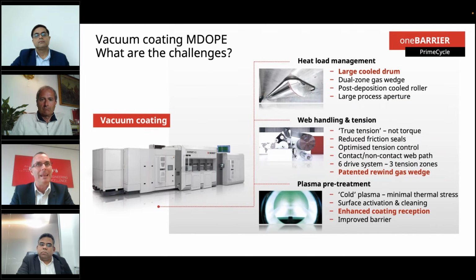We then move on to the metallization step of the structure. Typically, metallization on PE-based substrate is very challenging, as they're typically heat sensitive, extensible, and non-polar in nature. Now, MDO technology and primer application have certainly helped to improve some of the issues and limitations related to the extensibility and the surface polarity of the PE substrate.